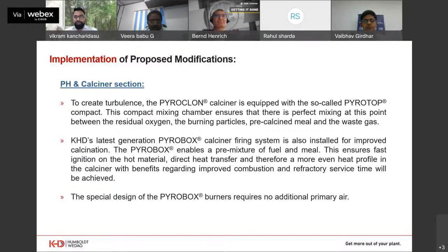And we have also installed a PYROBOX calciner firing system. This is also a patented design of KHD. It's a simple design, but unique, because the meal and fuel both are introduced into the feed box before entering the gas stream. So the pre-mixing already takes place, and then the pre-mixed material is uniformly distributed into the gas stream, which gives uniform heat distribution across the calciner. So it avoids the temperature peaks, and sometimes in old calciner burners, we have seen that the refractory fails too soon because of the high temperature. Because of this uniform heat distribution, this problem will not be there.